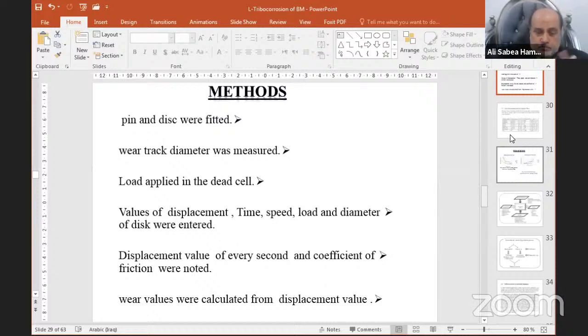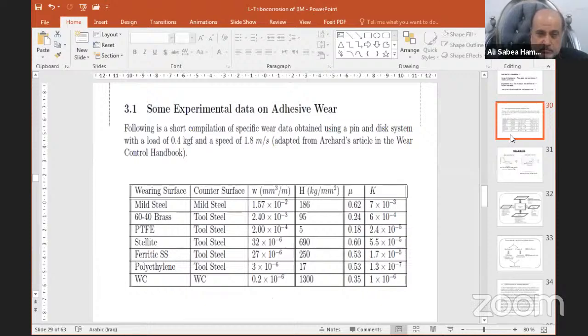This table explains the specific wear data obtained using the pin on disk system with a load of 0.4 kilogram force and a speed of 1.8 meters per second. The wearing surfaces are mild steel, 60-40 brass, polytetrafluoroethylene, and other materials with counter surfaces. For example, the wearing surface may be mild steel and the counter surface mild steel. Another example is 60-40 brass as the wearing surface with tool steel as the counter surface.